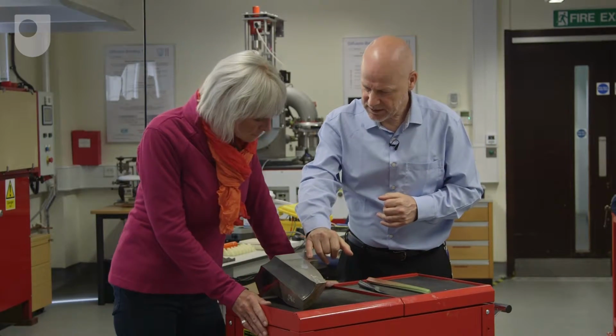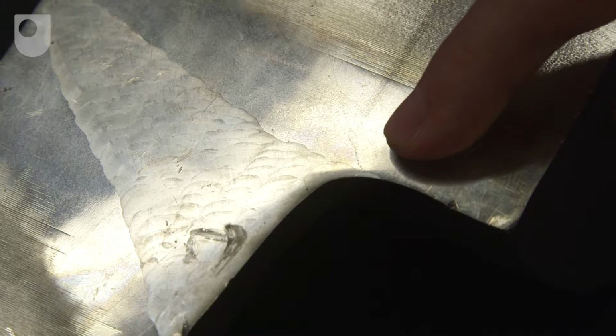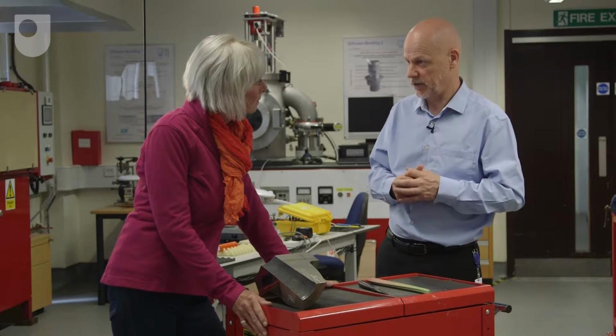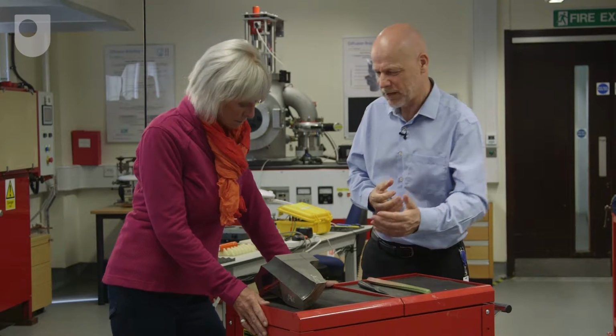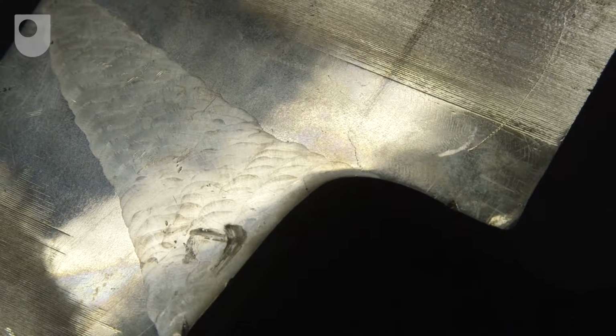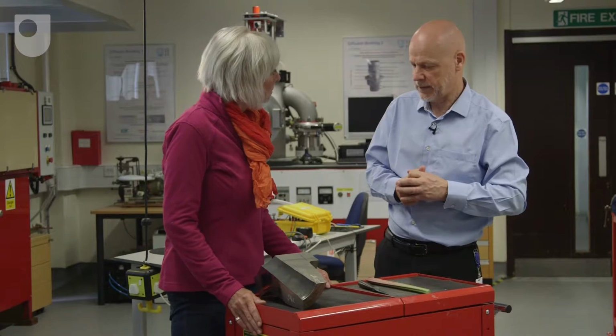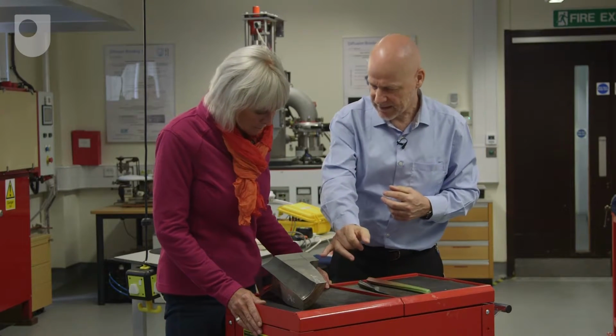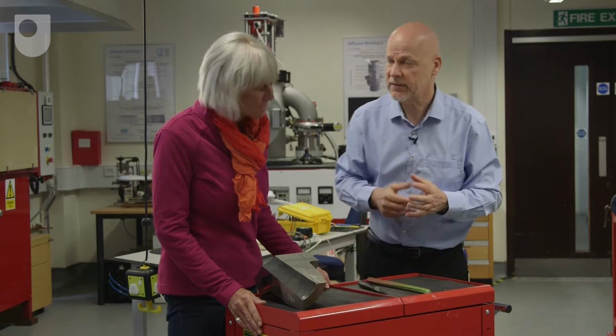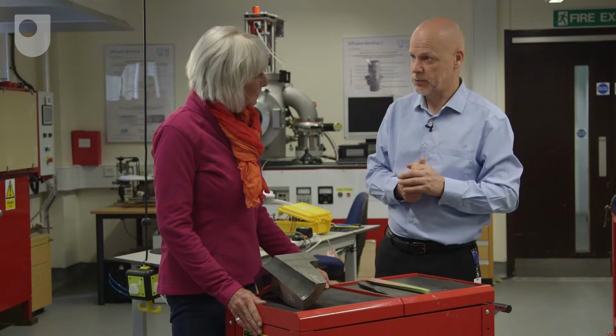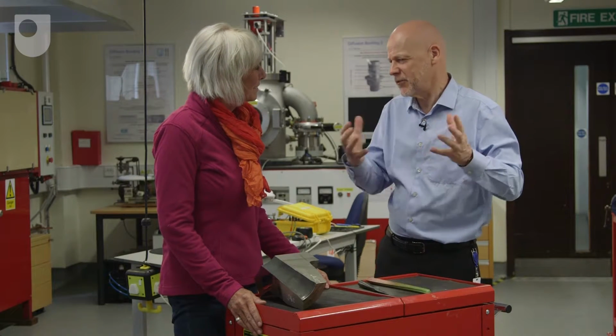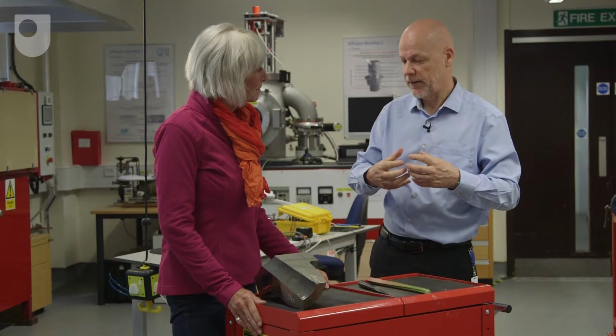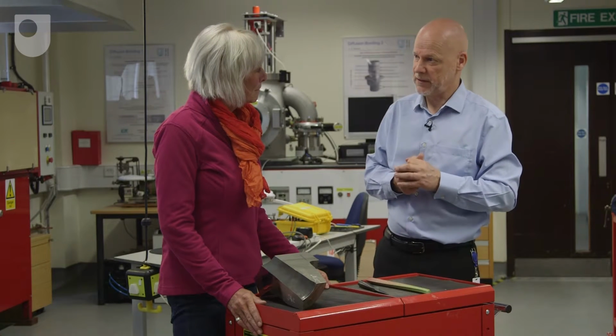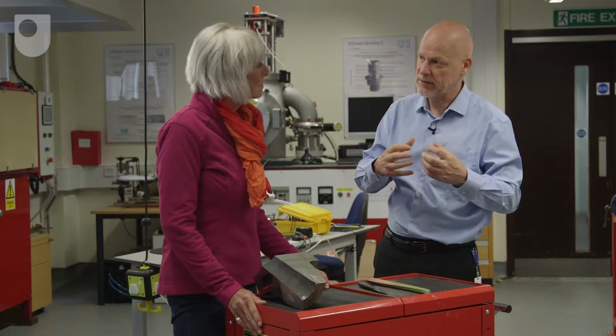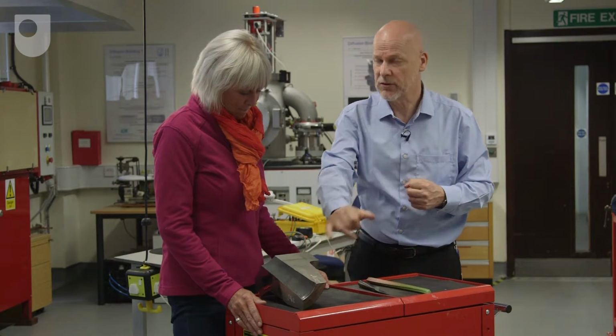Now, in fact, this crack was driven mainly by hidden residual stresses which are locked into the structure during manufacture. So the welding process, which you can see this very large weld here, is a very aggressive, heat-intensive process which can introduce very large strains and stresses. And it's the relaxation of those stresses which is actually causing this crack to appear by a mechanism called creep. Okay. Now, creep is something which happens at high temperature, slow deformation, but you can develop within the material cavities and micro cracks which can join up to create a macroscopic crack like this.